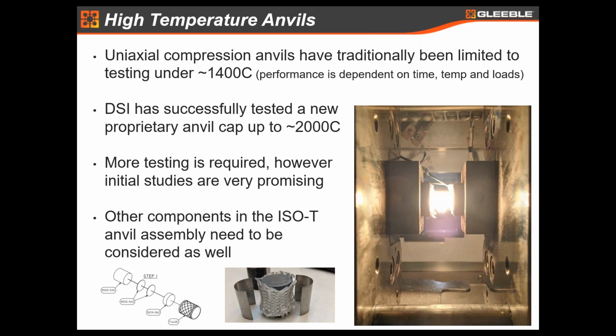It's early. We've got some more testing required. However, it's very promising. Actually, the limitation isn't so much the anvil cap, it's the anvil backers, the sheathing, some of that kind of shell around that specimen. But at 2000 degrees, it looks like it's been working. More testing is required, but you can look for something coming from us pretty soon. We're looking at starting to add part numbers and get those incorporated into our systems.